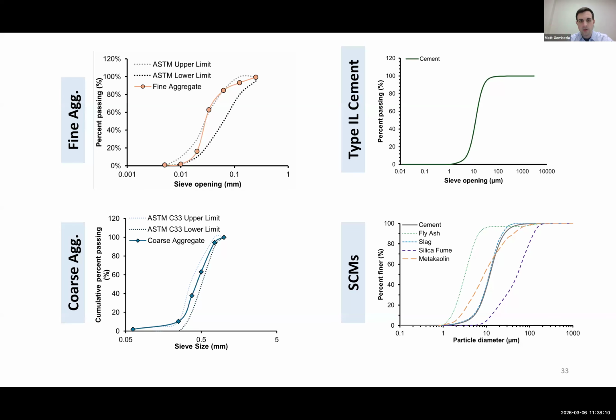So here you can see the particle size distributions for some of the materials: the fine aggregate with the ASTM C33 limits, also the coarse aggregate, the IL cement, and then some of the SCMs that were used as well in the bottom right.